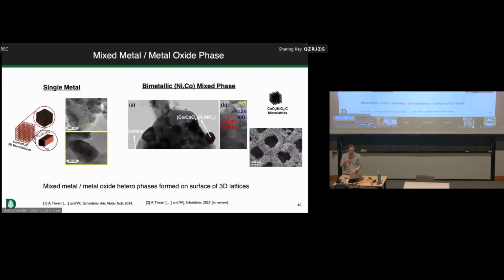One of them is by having the mesoscale structure, and the second is by changing the micro or nanoscale structure at the surface. What we end up developing actually after it's been converted at a high temperature is some mixed phase. The mixed phase in this case often has the most interesting electrocatalytic properties. So it's a mixture of metal and metal oxide at the nanoscale, as well as the carbon to be able to essentially extract the current or inject the current from our device. But at the same time, we're controlling essentially this high surface area form of the cobalt oxide or nickel oxide.